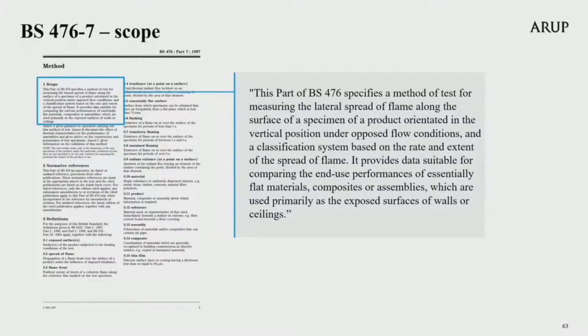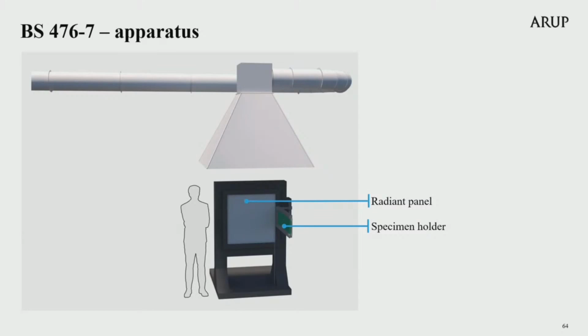The scope section of Part 7 states, this part provides data suitable for comparing the end-use performances of essentially flat materials, composites or assemblies, which are used primarily as the exposed surfaces of walls or ceilings. The scale of apparatus used in the Part 7 test is very different to the other 3 national reaction to fire tests, and relatively speaking is a much larger test. However, it is still important to note how much smaller this sample size is when considering the scale of a cladding panel used in construction. I will show an image to help understand this later.